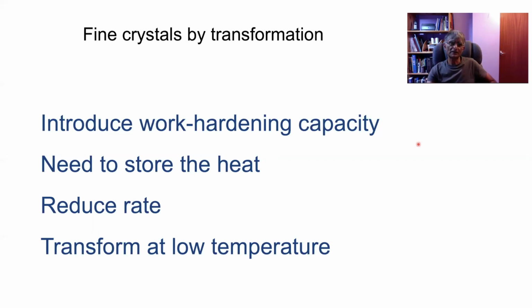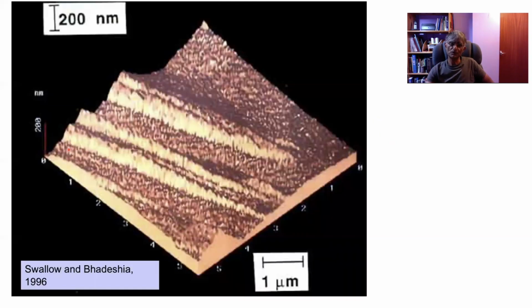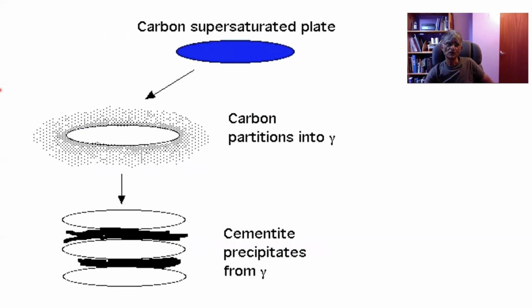Okay, and the work hardening capacity, if we choose bainite, would come in from the retained austenite if we add silicon to our alloy. So this is the shape deformation due to the bainite transformation, and it introduces a stored energy term of the order of 400 joules per mole, which is quite large. And as I said to you, we will cut the reaction off at this point so that we end up with a mixture of carbon-enriched austenite and bainitic ferrite plates.